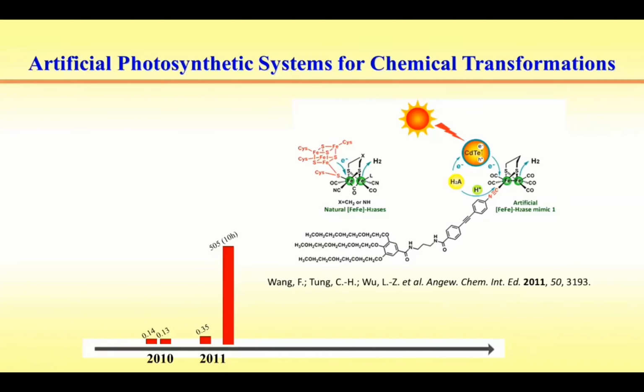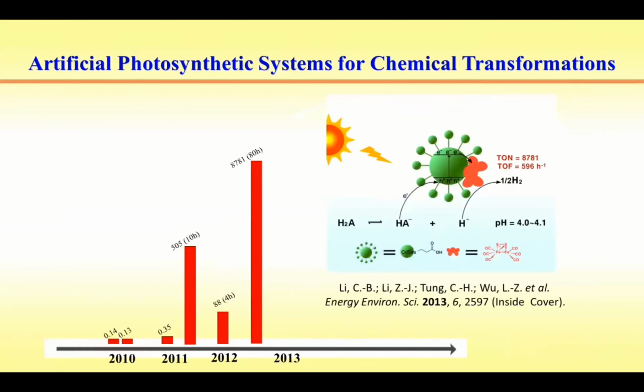A synthetic hydrogenase mimic, even the most popular one that will generally decompose within 1 hour of irradiation, could serve as an effective catalyst for hydrogen generation. This exciting result encouraged us to develop an interface-directed assembly for hydrogen evolution. The surface affinity of the water-soluble quantum dots allows for the interaction with the sulfide atom on the hydrogenase mimics in aqueous solution. Indeed, upon light irradiation of these self-assembled systems for 80 hours, the assemblies enable hydrogen production with a turnover number of 8,000 based on the hydrogenase mimics.